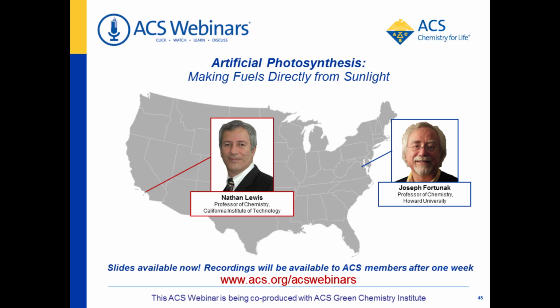Our solar to measured lower heating value free energy of hydrogen production, where we take a good solar simulator and measure all of its intensity and then measure all the lower heating value or free delta G energy content in the hydrogen we produce, is over 10% in these systems. So a factor of better than 10 that really enables you to start thinking about not worrying about trading food for fuel, because the land area constraints are so much relaxed by that big order of magnitude reduction in land area coverage.